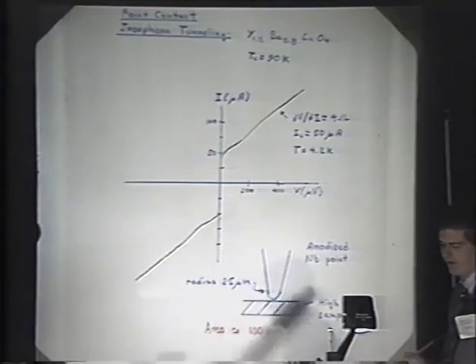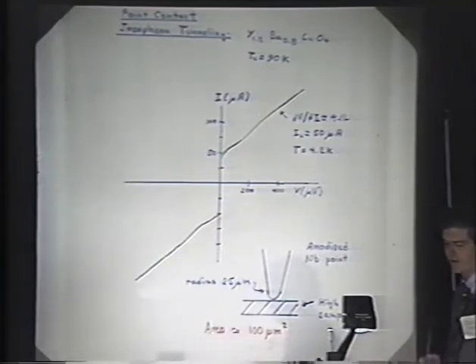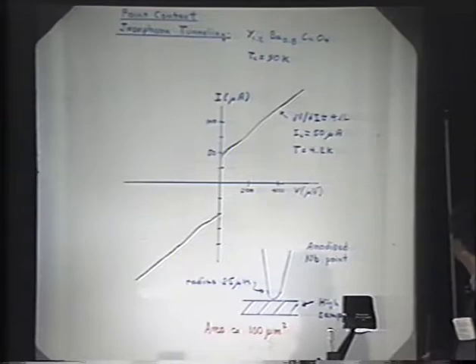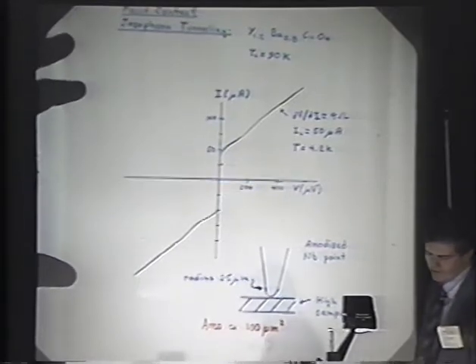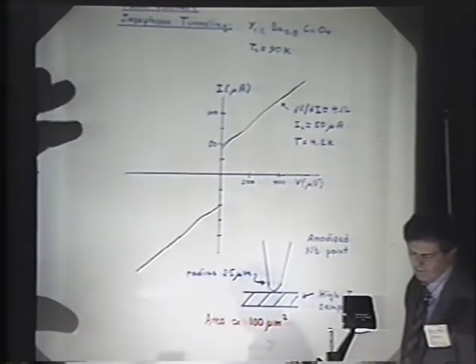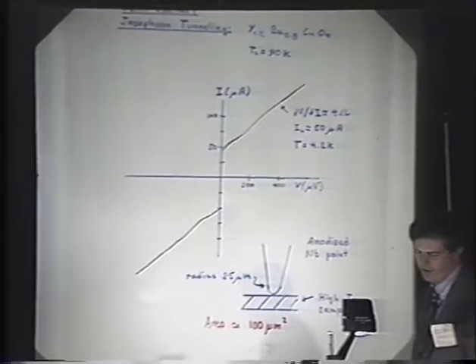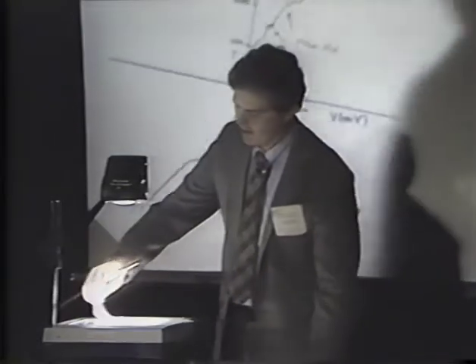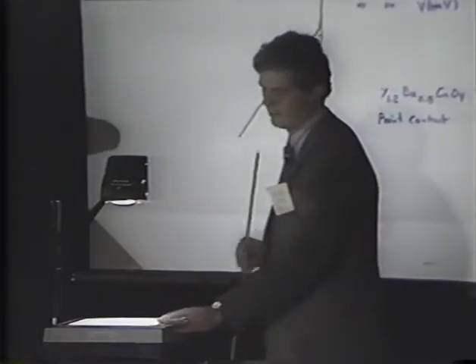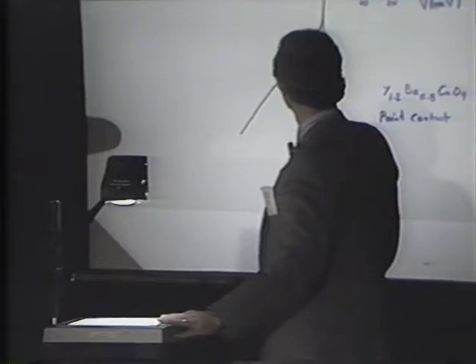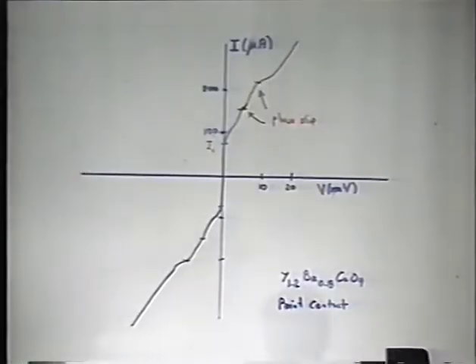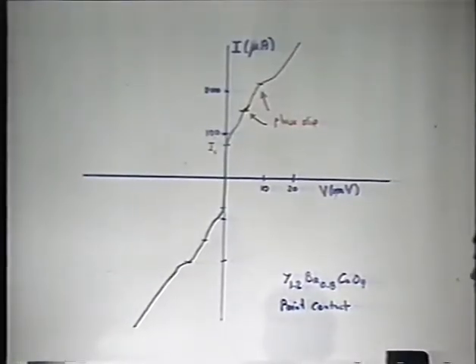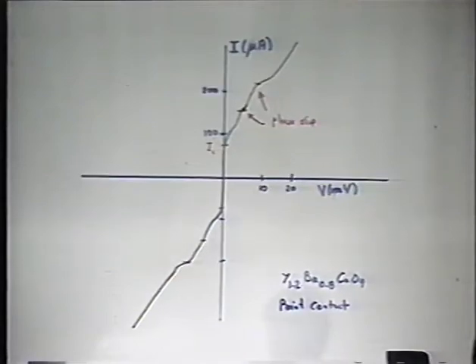It was a niobium tip with a little bit of niobium oxide on it, and we got this very pretty Josephson supercurrent that you see here with about a 50 microamp critical current. If we blow up that particular characteristic, you can actually see little breaks in the slope if we look out at higher voltages, and these breaks in the slope are in fact characteristic of some phase slip centers.